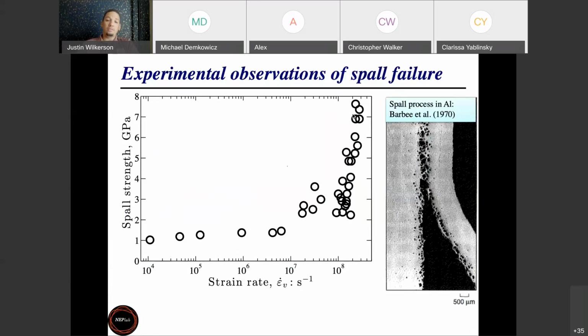It can only do that for a few nanoseconds, really. A strain rate of 10^8 per second means that this material is going to completely fail in about a nanosecond or so. Or at least it'll get to 10% strain in about a nanosecond. And we have this incredibly strong rate sensitivity associated with spall strength. And so we want to understand what's the physics that really governs that. Can we model it? Can we control it from a material design standpoint?